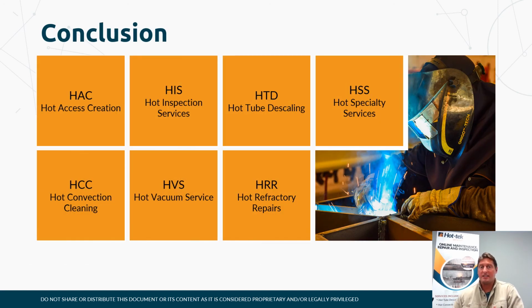So that concludes the presentation. We covered our access creation, which is pretty much a part of all except for the refractory repair, which is a different style access creation, our hot inspection services, and the benefit of being able to use that in up to 2,500 degrees. Our hot tube descaling, being able to remove loosely adhered scale on process tubes on both single and double fired heaters. The convection section cleaning, removing the fouling on those finned and studded tubes.